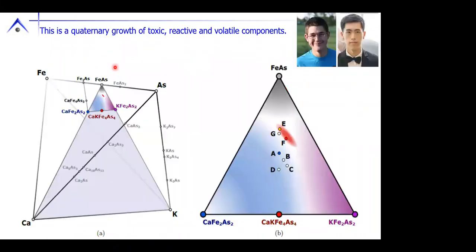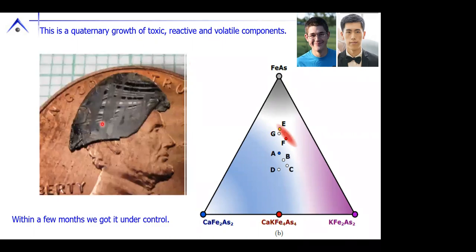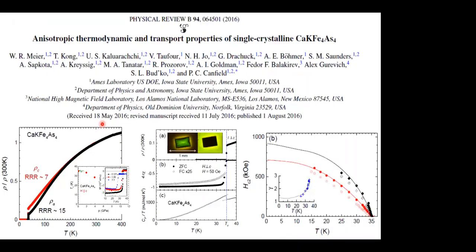Okay, and these two fine gentlemen, William Meier and Tai Kong, spent a couple months actually trying to figure out where we could find the exposed liquidus surface in this true quaternary phase diagram, which we can then map onto a pseudo-ternary phase diagram. And by identifying this as a region of primary solidification, we could grow single crystals. Okay? With single crystals in hand, we could look at the basic properties.